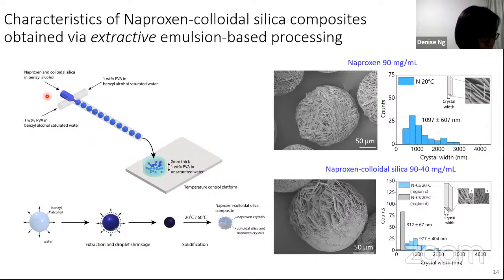In this case, naproxen and colloidal silica are then emulsified into monodispersed droplets using a microfluidic device, again with benzyl alcohol-saturated water. This helps to prevent any extraction from occurring during this process in the tube, and it then only occurs within these thin film conditions at the outlet here. So this helps to prevent any clogging within the tubes. What happens after the droplets have been collected into this thin film is that the benzyl alcohol is extracted into the film, and this results in droplet shrinkage, and therefore the naproxen in it begins to supersaturate and crystallize.